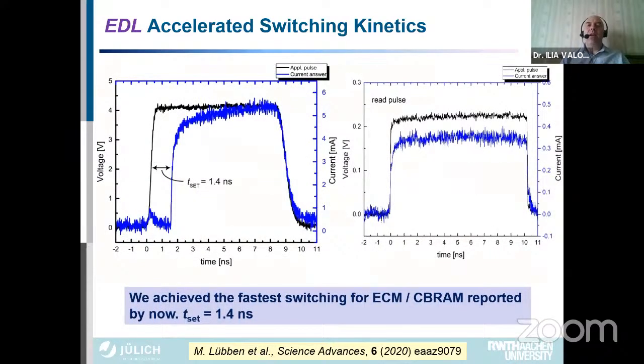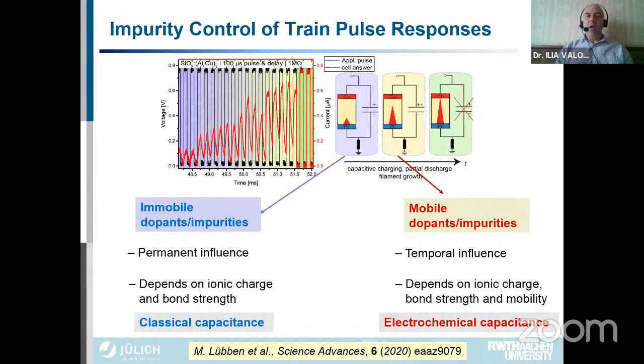At very high voltages, both come together because the field is so high that the field acceleration applies to all materials. And we were able to achieve the fastest switching practically for ECM, electrochemical metallization memories, of about 1 nanosecond. At least this is the resolution. We are at the moment working to detect faster switching, but at the moment we can detect 1.4 nanoseconds, which is orders of magnitude faster compared to doped materials. I'll give you also in the last slides the impression of the influence of these additional charges, mobile and immobile, on the matrix and how they influence the neuromorphic functionalities.